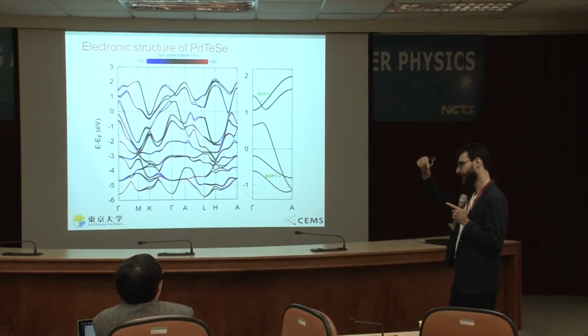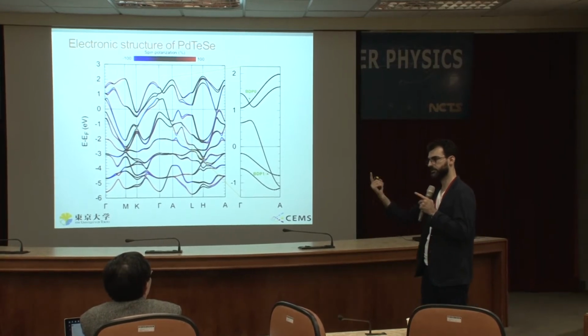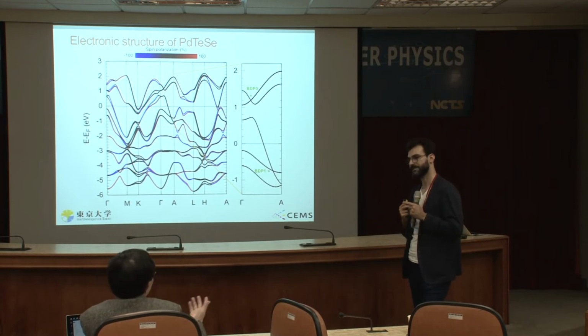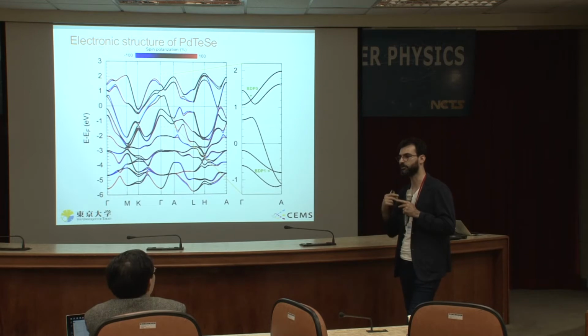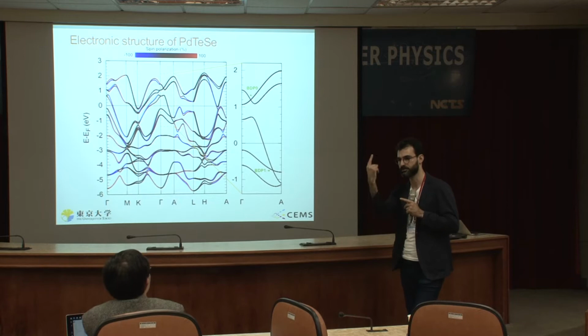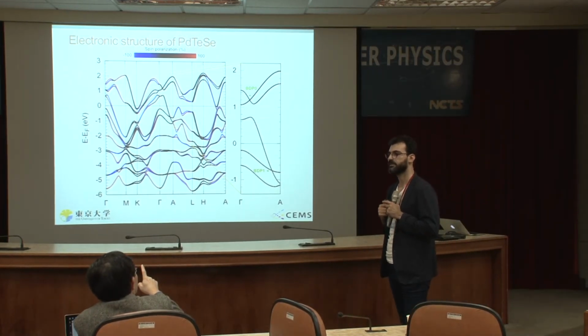So actually, here rotational symmetry plays the role of inversion symmetry. So when you break inversion symmetry, it will still be there. It compensates the breaking of inversion symmetry by having this constraint that you put on this axis, because this is the rotational axis and this is the special axis. Okay, so that's fourfold including spin. Yeah.